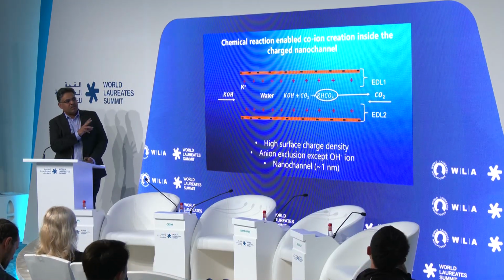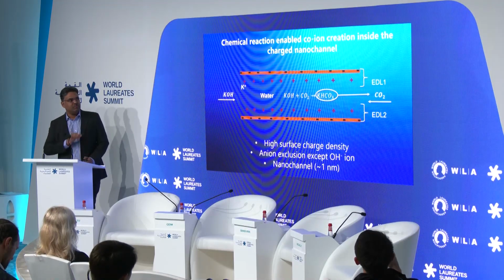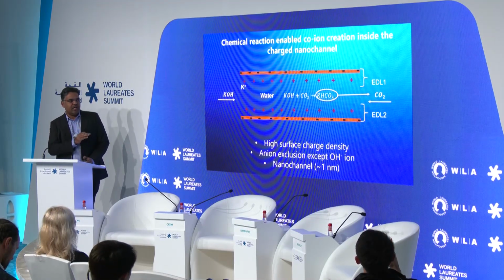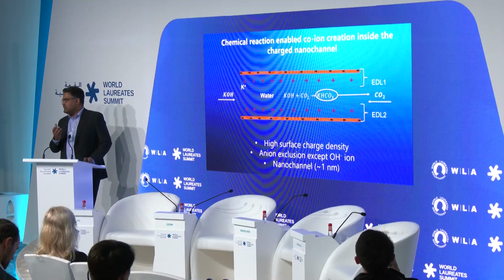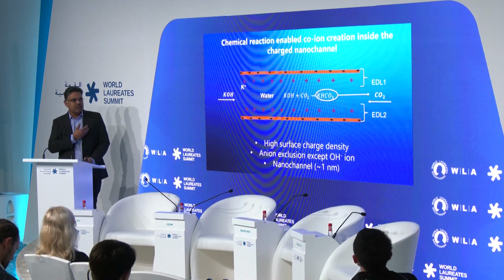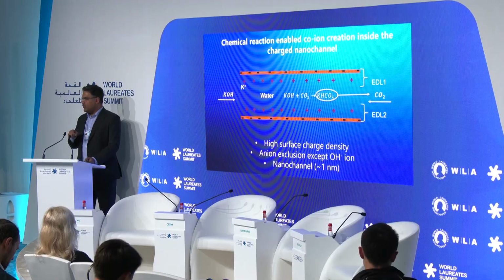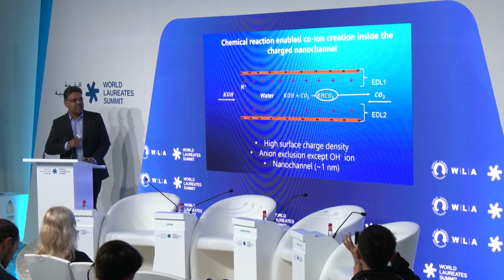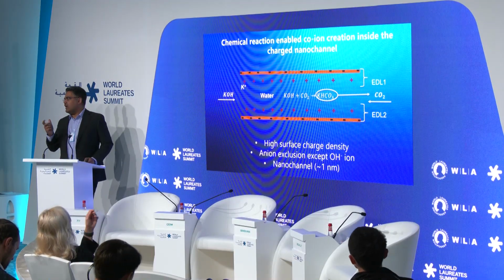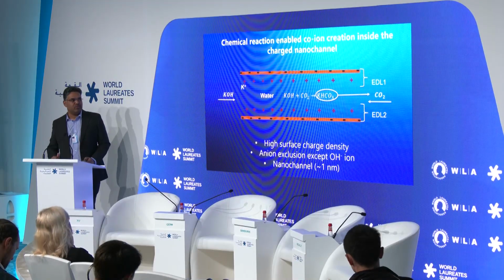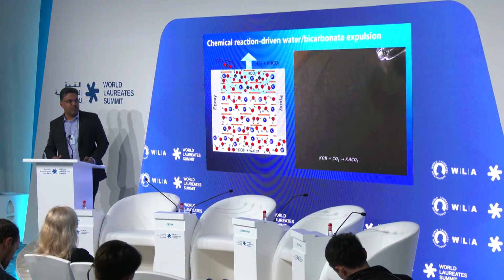For such a process to occur, there are three conditions we need. The membrane has to be highly negatively charged. Because of the negative charge, it also excludes all the anions except OH minus ion, because we need to have that reaction inside. And the channel size should be 1 nanometer or as minimum as possible to get this phenomenon maximum.